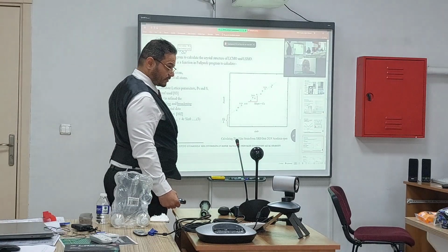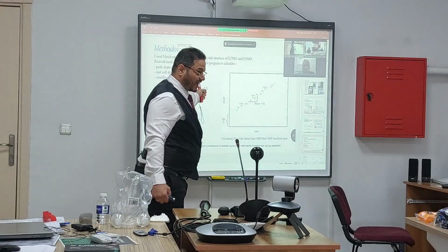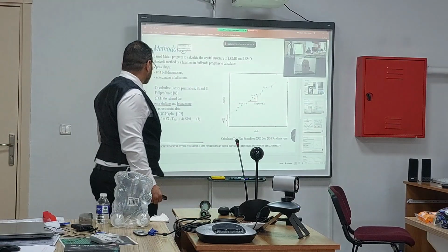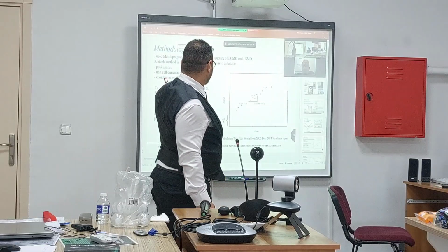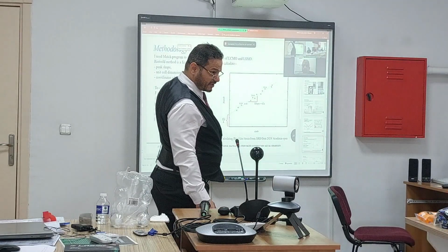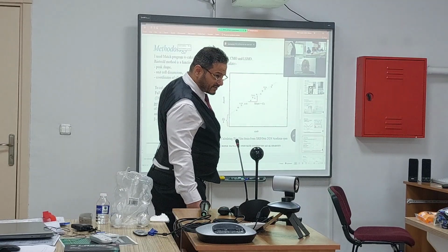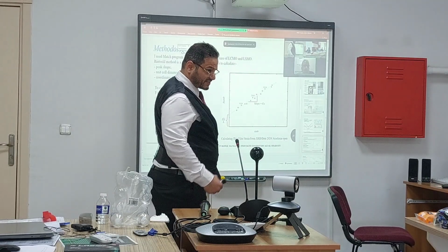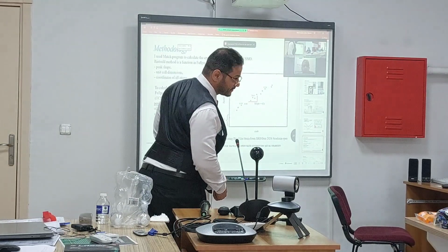Let me, okay. To calculate the lattice parameters, particle size, and strain, FullProf used Thompson-Cox-Hastings to refine the peak shifting and broadening of experimental data. Don't forget Williamson-Hall helped to calculate the average particle size and strain for all of my peaks.